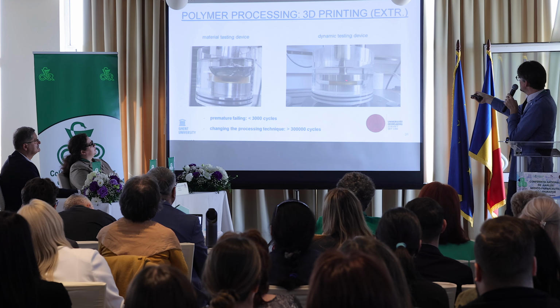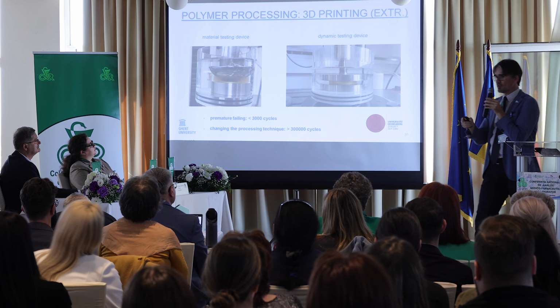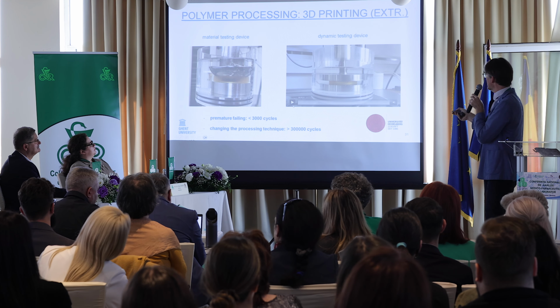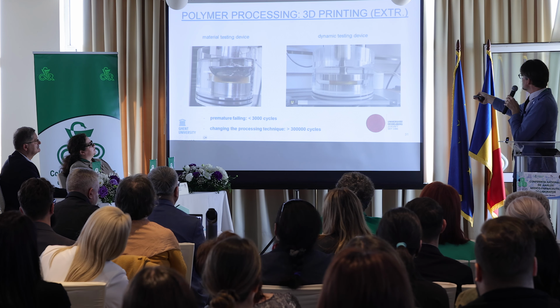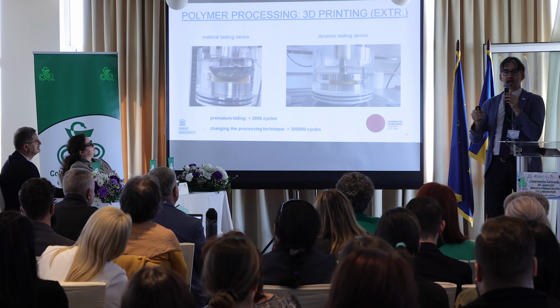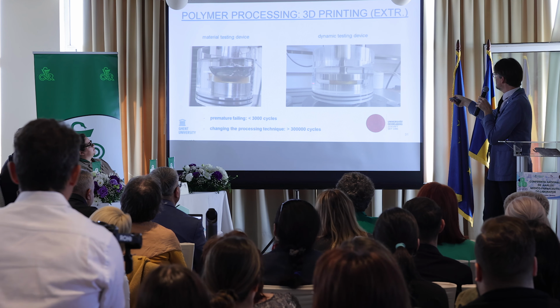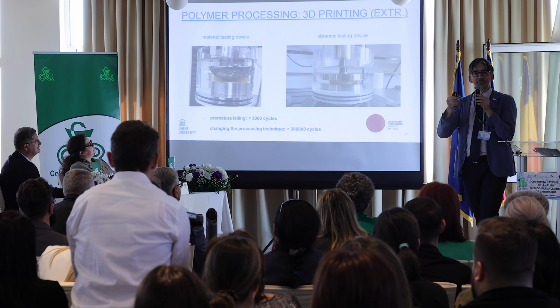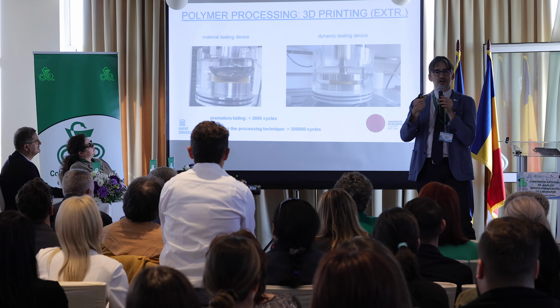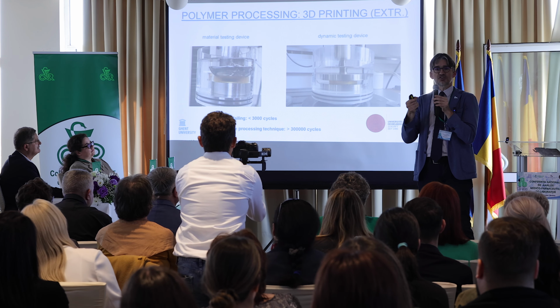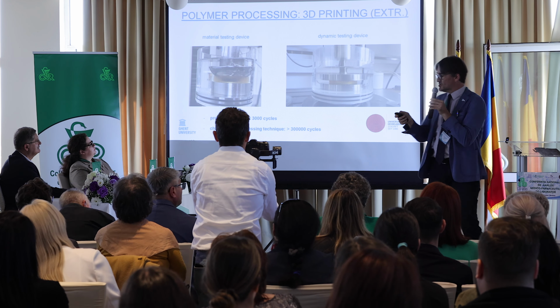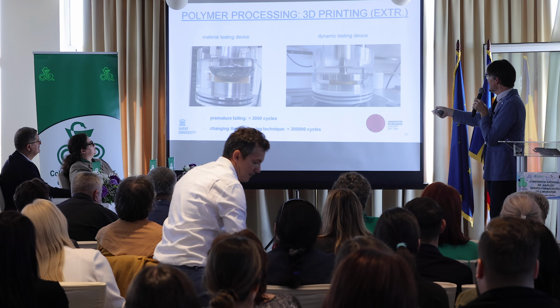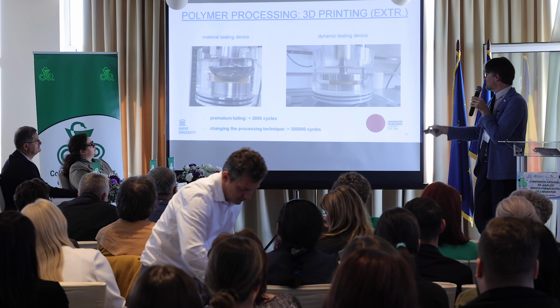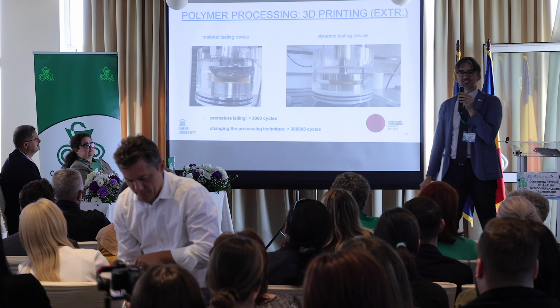On the right here you see a dynamic testing device, and if also that one can be opened would be very nice. Thank you. So you see directly that the frequency is much higher, which means that these different types of setups mimic quite well what the loads are that a human meniscus implant would be facing. But of course, you also see that if you look at this finding here, that each of those scaffolds failed after less than 3,000 cycles.